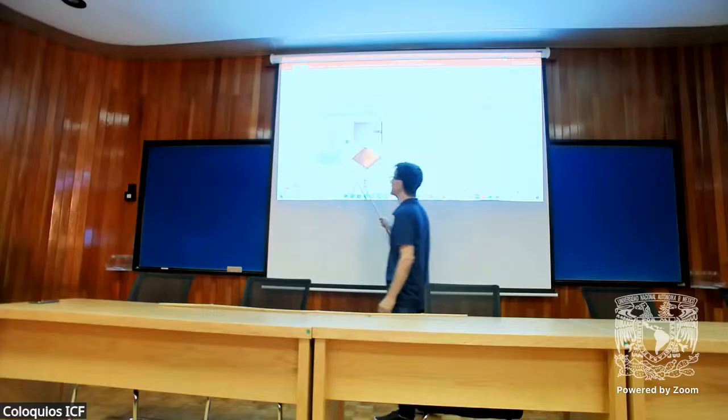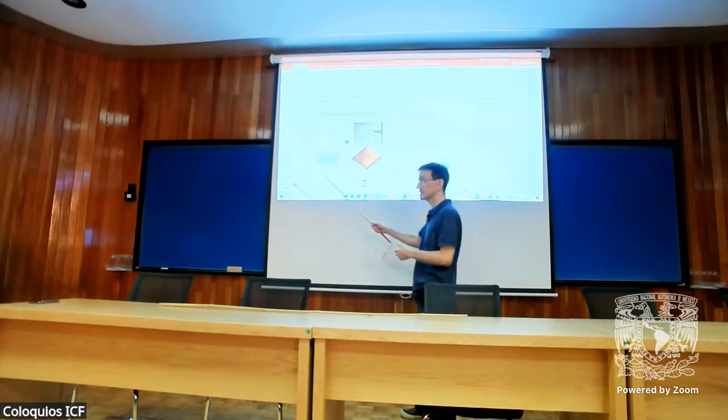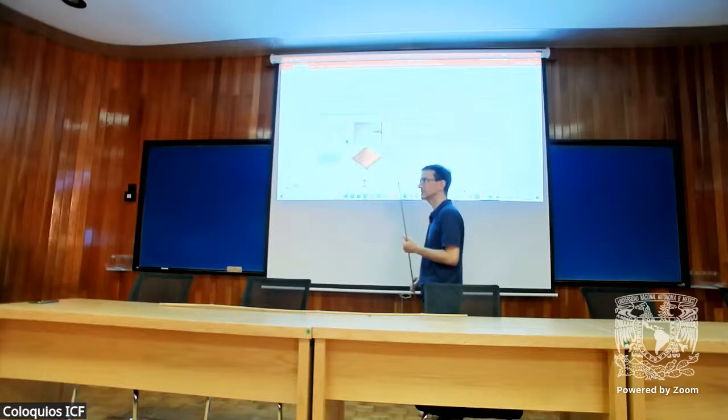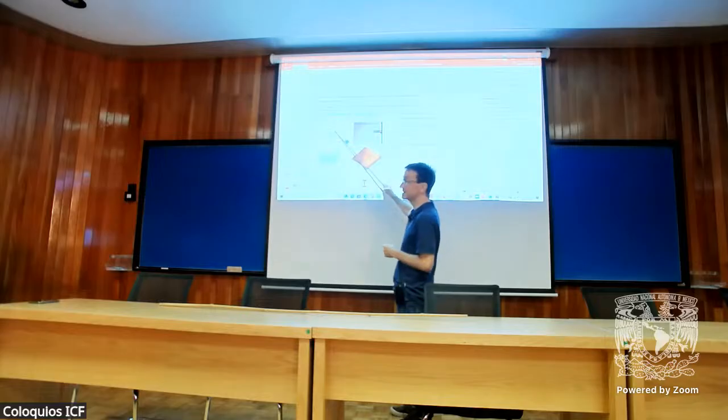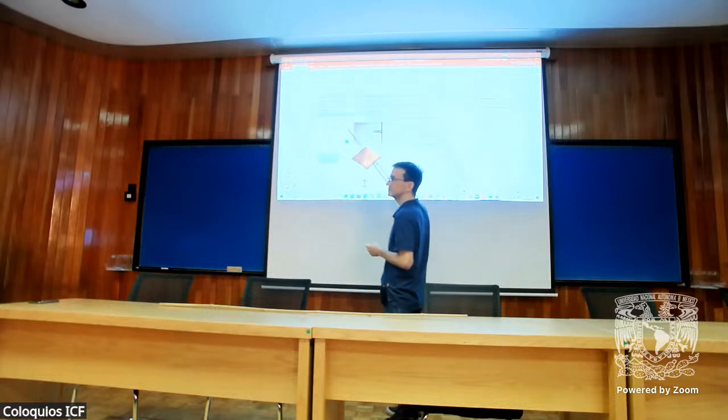In this case, we needed really high currents. So what we did actually, that's explained in detail in that instrumentation paper, we put the sample inside the ion source. And then the current is really high. This is why it's cesium, because we only have the cesium ions inside the ion source. And there is a shape here. The fluence is not uniform.